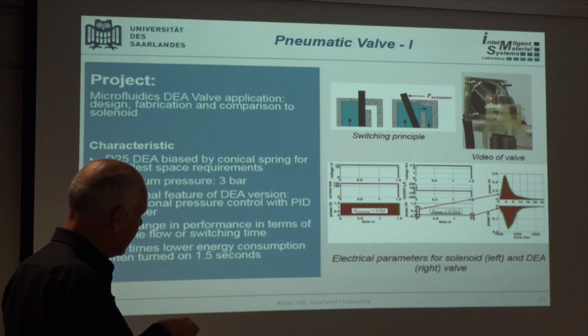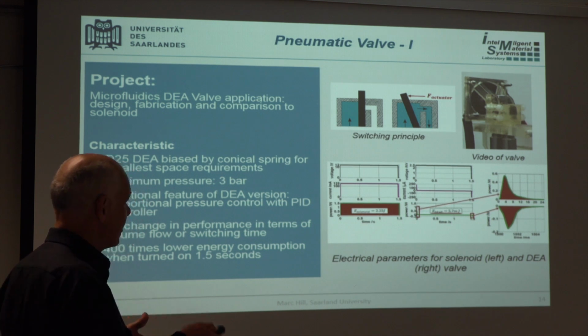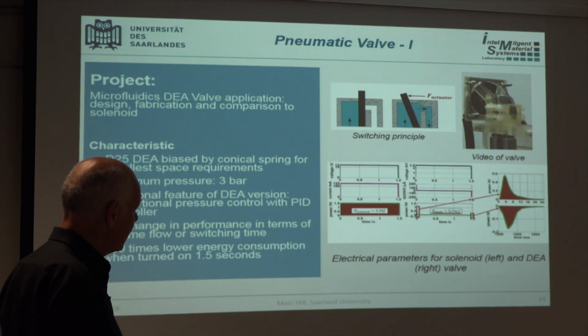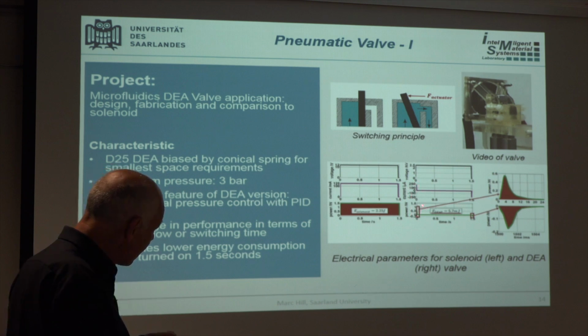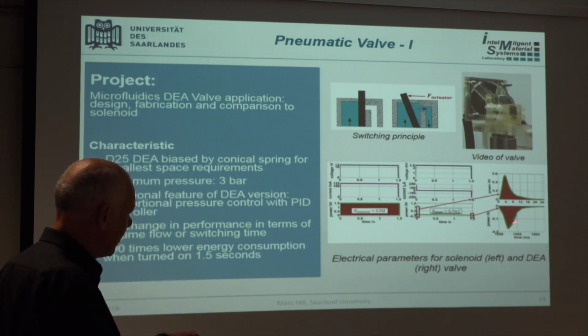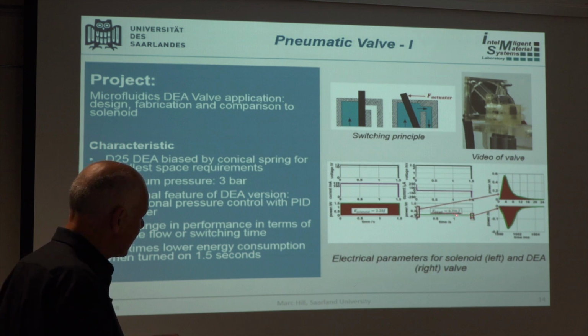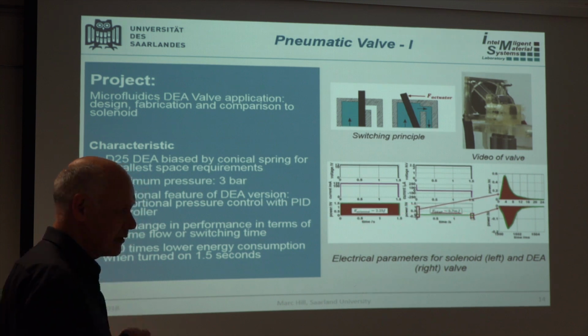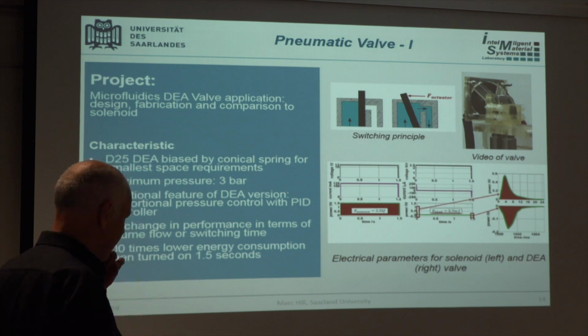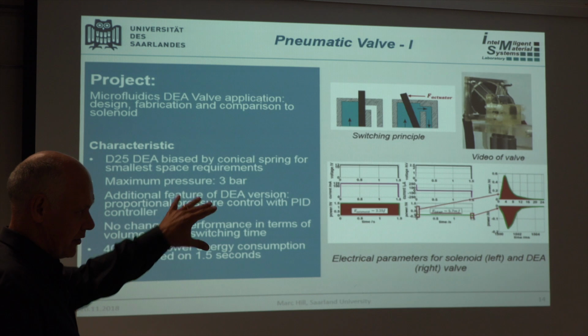When we do the same thing with the electroactive polymer, we see that current is only needed to charge the electrode. So there's a little spike here at the beginning, and when you discharge, you could theoretically even get some energy back, even though this is very small amounts in this order of magnitude here. But when you zoom in on these curves and blow up the little spikes, you see here's a little area. When you calculate the energy that you need to do that, even without taking into account that we could harvest some back here, it is on the order of 5.7 millijoules. So there's a factor of roughly 400 or 500 in terms of energy conservation that would be possible for such an application.